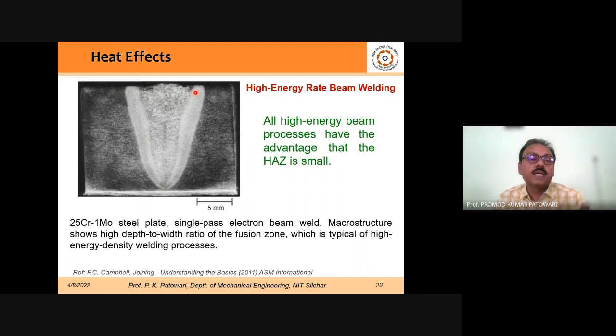So in that way, even a thicker plate you can join up to the depth very effectively. But on the other hand, the weld joint is not very well spread, and we do not want that. We want only very localized heating, so that only at that area you can make the changes, and the rest of the material should not get affected much. Even by a single pass you can reach quite deep and get the material welded, by applying a lesser amount of energy. And if you apply lesser energy, it's quite obvious that the heat energy will get dissipated less, and you will get a smaller heat affected zone.